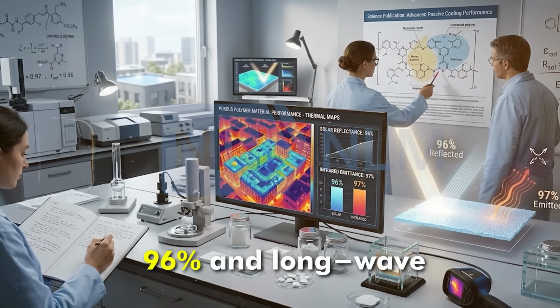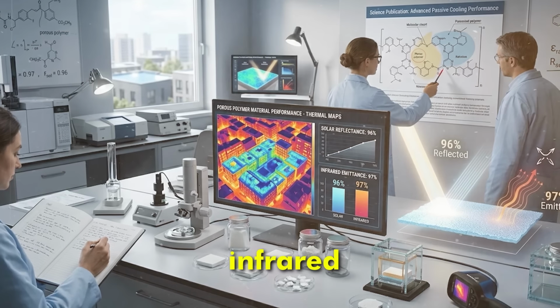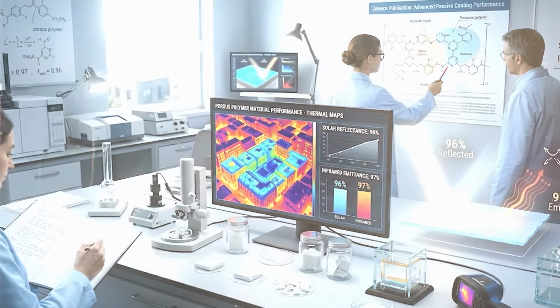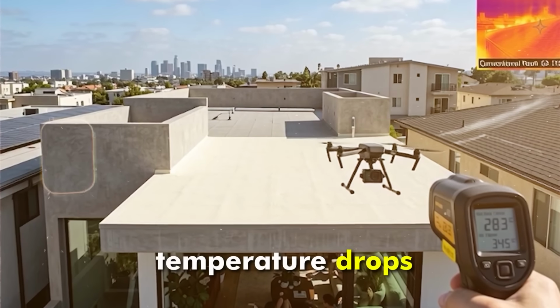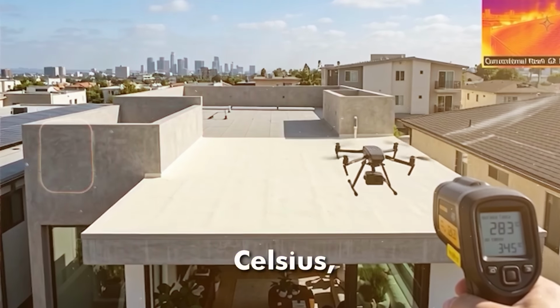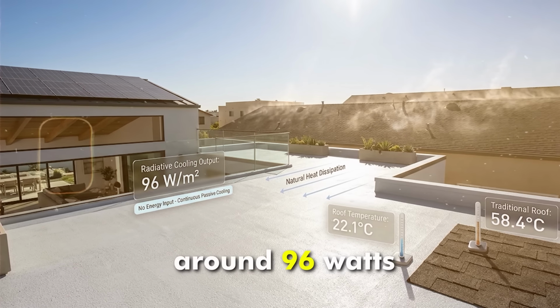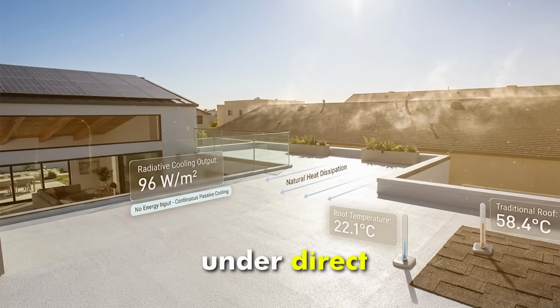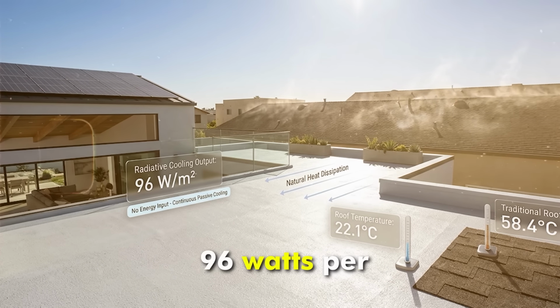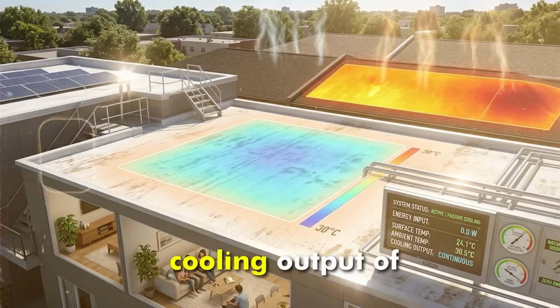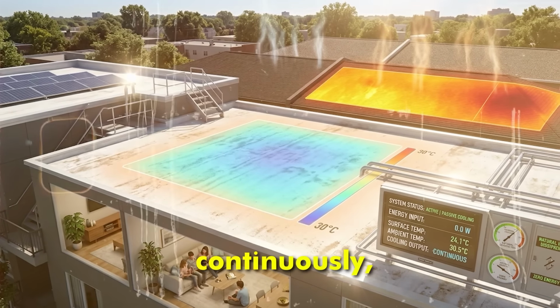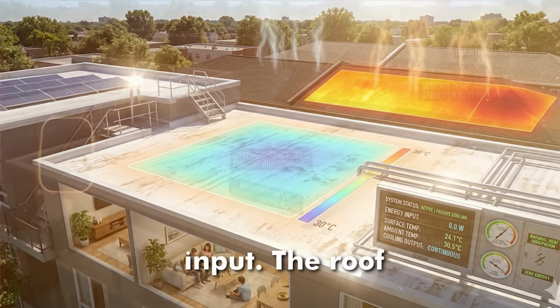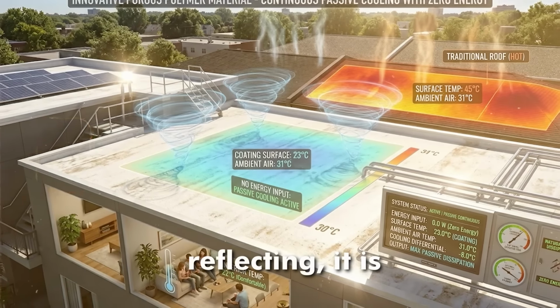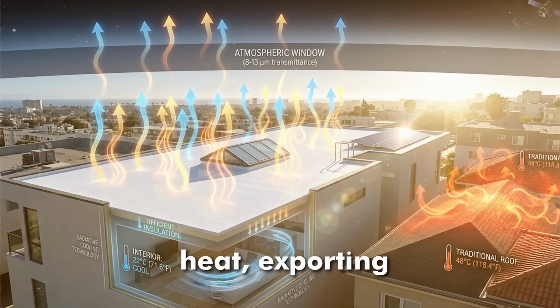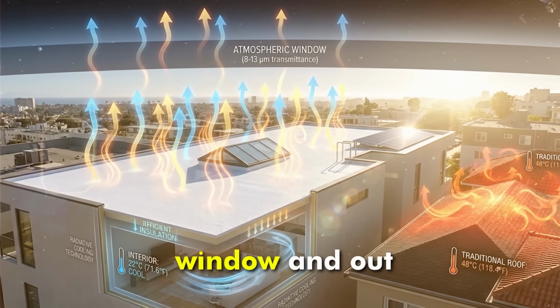Research published in Science documented solar reflectances of 96% and long-wave infrared emittances of 97%, with sub-ambient temperature drops of approximately 6 degrees Celsius and cooling powers of around 96 watts per square meter under direct sunlight. 96 watts per square meter. That is the cooling output of the surface, measured continuously, with no energy input. The roof is not just reflecting, it is actively removing heat, exporting it upward through the atmospheric window and out into space.